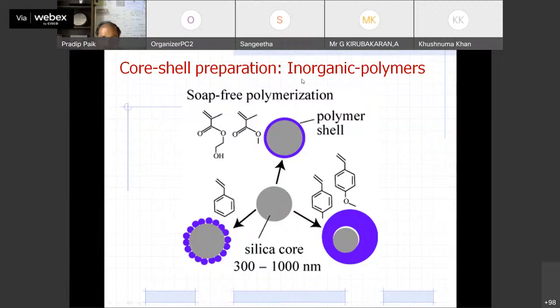Core shell preparation with inorganic materials, for example polymer shells and silica as the core. What size will you take? Let's say 300 to 1000 nanometers, and you will use the polymerization method. The silica will have negatively charged OH groups, and that negative charge attracts the polymer materials and allows the deposition.